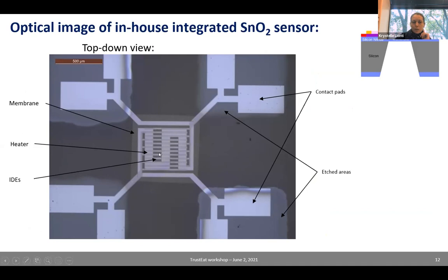On top of these fingers, we deposit the MOS by spin coating, so it goes everywhere. So we are going to just reveal the contact pads here by ion milling. Through these two pads, we are going to flow current to heat up the heater. And then through these two pads here, we can apply a voltage and monitor the resistance of the MOS.